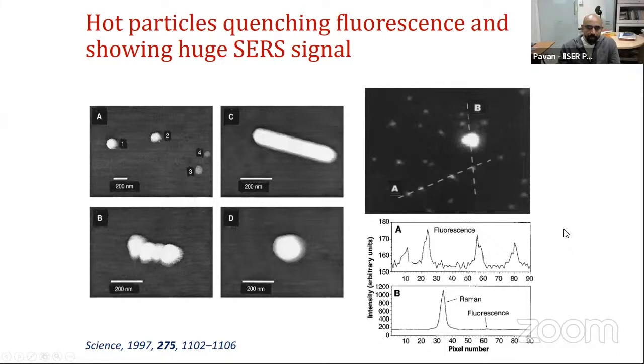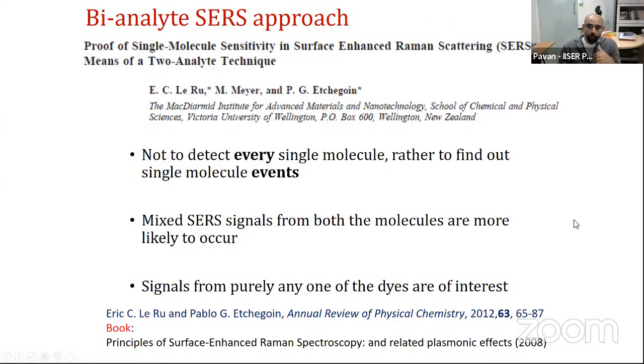So going further, this particular approach was revisited, and a technique called the bianalyte approach was used. In fact, Le Ru and Etchegoin, two physicists, actually revisited this problem and came out with a fantastic analysis of the statistics. They came up with something called the bianalyte technique, where you don't need to detect every single molecule, but rather you will find out the single molecule events. In fact, this is an approach we also take, and this is most of the time the physicist's approach, where one is studying single molecule fluctuation in Raman scattering. This is the approach which is now extensively used.